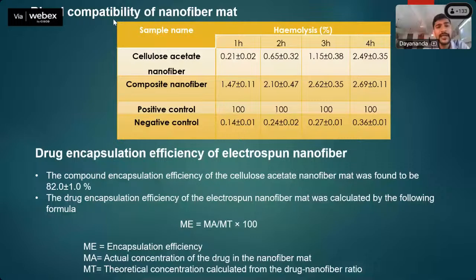This nanofiber mat was tested for hemolysis. The composite nanofiber, after loading the compound, had a hemolysis percentage higher than the pristine cellulose acetate nanofiber mat—it was just 2.69%. A nanofiber is considered biocompatible if the percentage hemolysis is less than 5%, but this could still be acceptable.